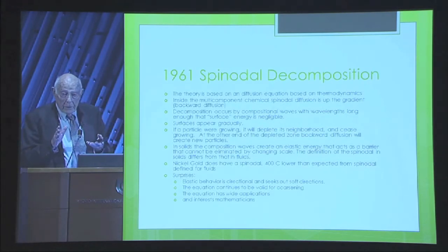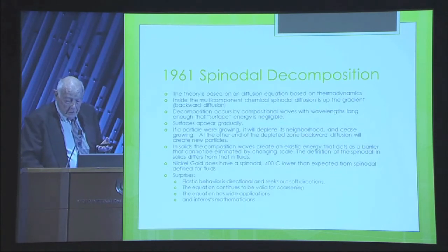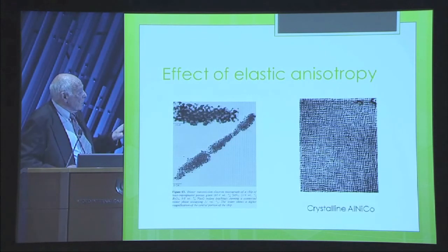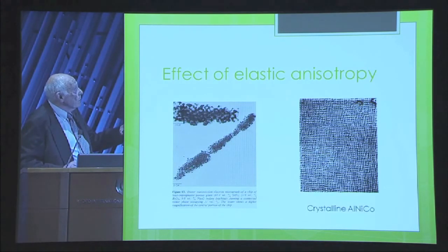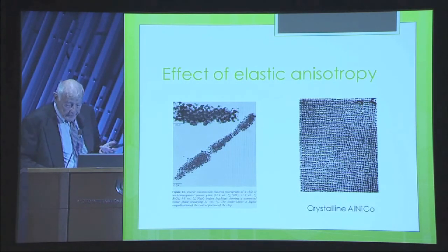In a crystal, there are soft directions and hard directions, and here is spinodal decomposition in a glass, which is the same in all directions. And so this is now made visible by impregnating liquid lead into a glass that had undergone spinodal decomposition. Here's a magnetic alloy, alnico, and you can see that within this crystal, the precipitates have lined up beautifully.